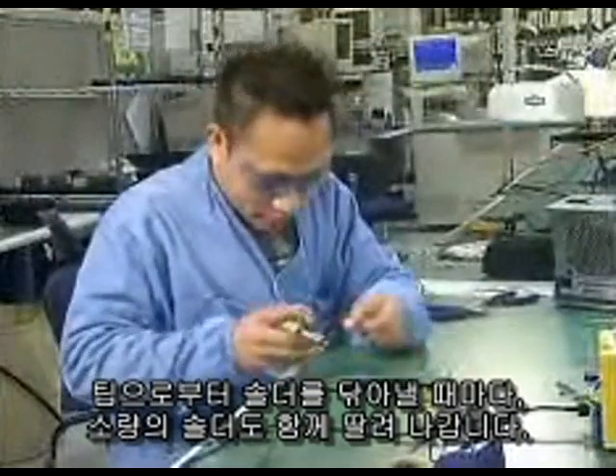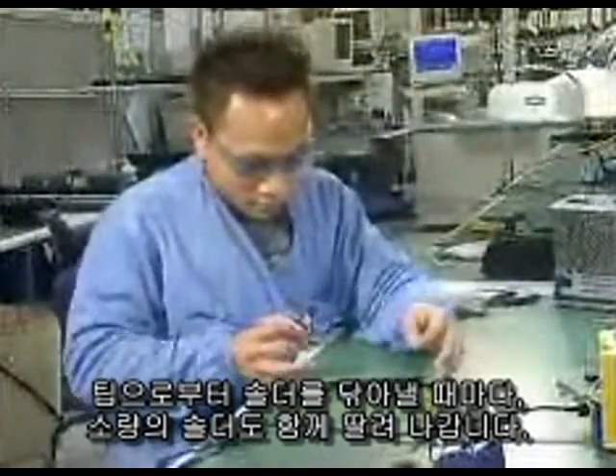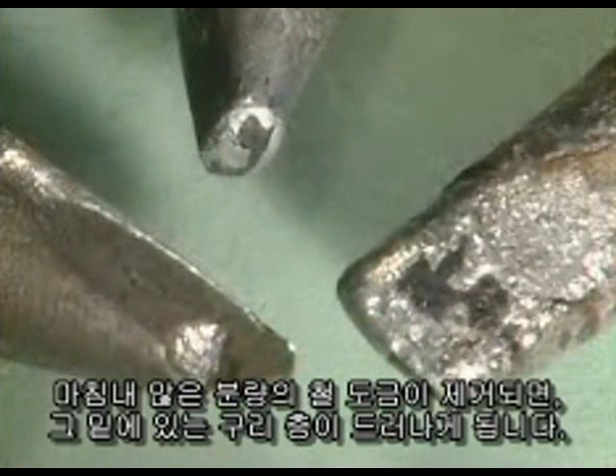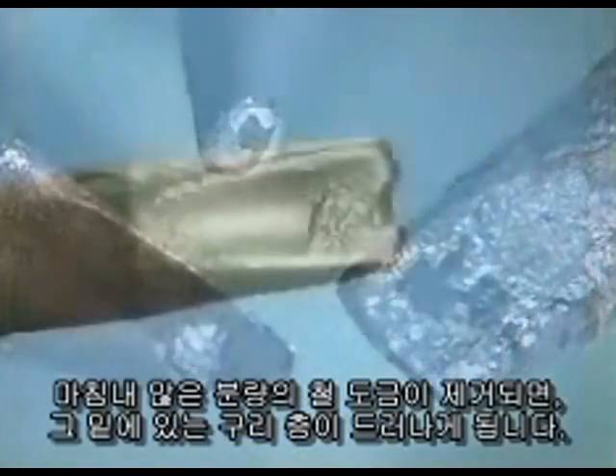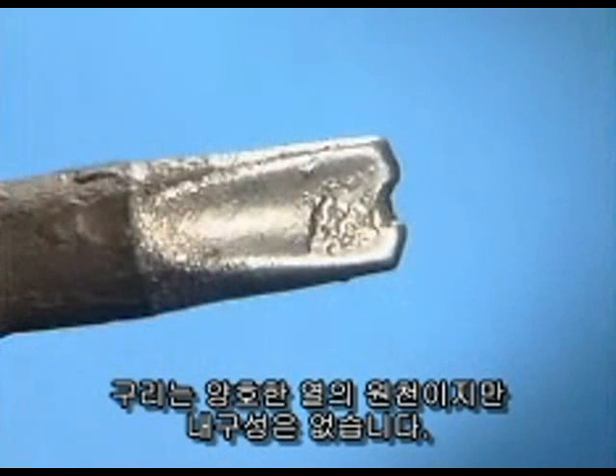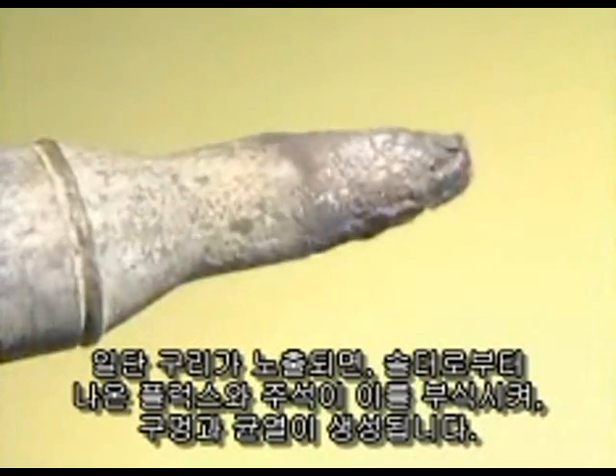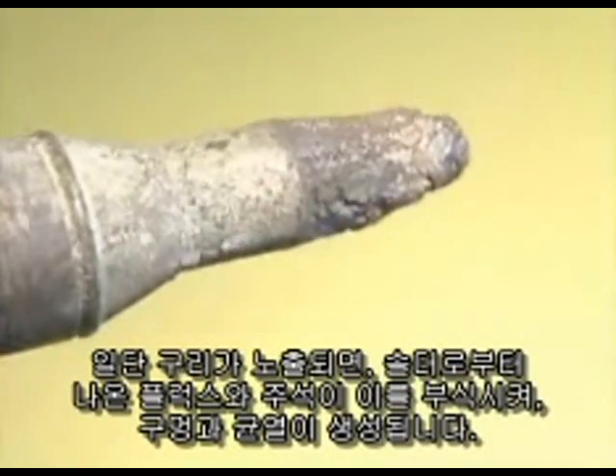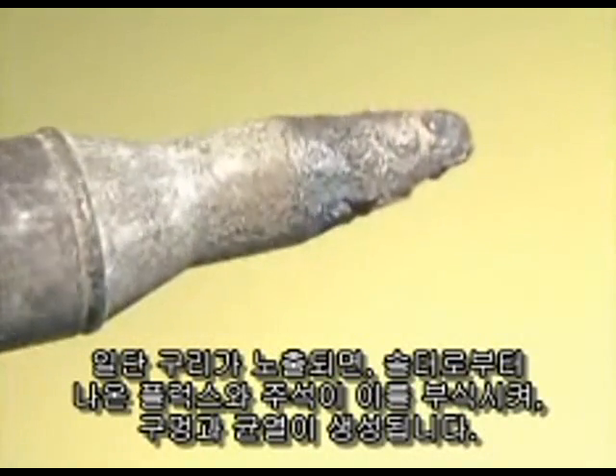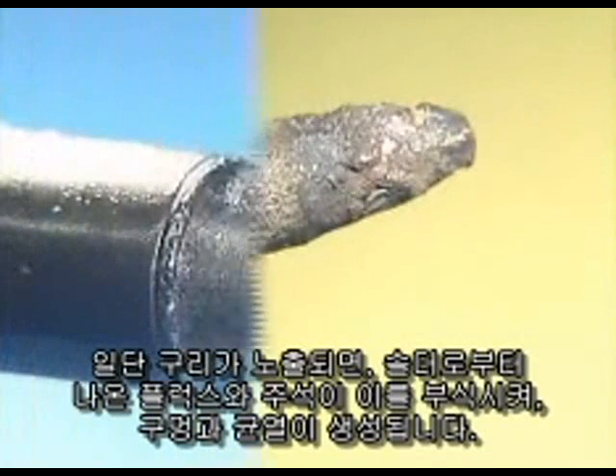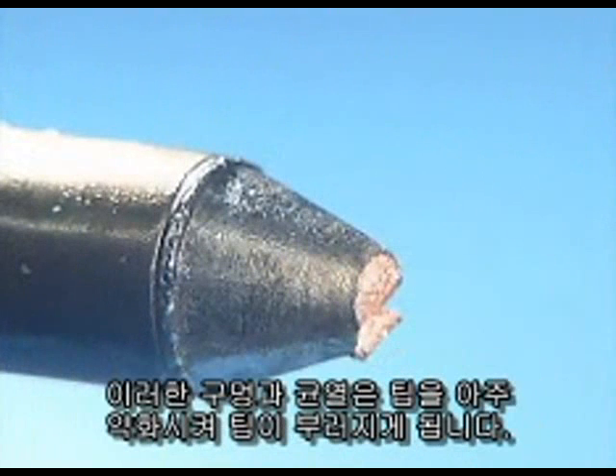Every time the solder is wiped from the tip, it takes a little bit of the iron plating with it. Eventually, it will remove enough iron plating to expose the copper that is underneath it. Copper is a great heat source but is not very durable. Once the copper is exposed, the flux and tin from the solder corrodes it, creating holes or cracks. These holes and cracks can weaken the tip so much that the tip may just snap off.